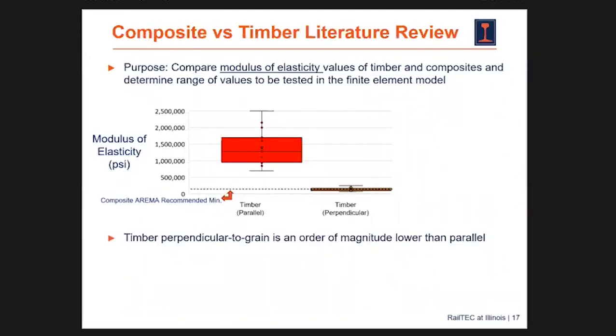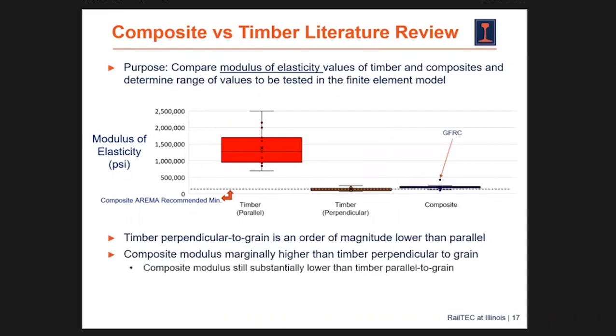So where do composite ties fit relative to timber? If we look at modulus of elasticity, the first thing we notice when we compare parallel to grain to perpendicular to grain, that again, I alluded to this, there's an order of magnitude difference. It's about 1/10 the level. So that means it's a lot more squishy. And composites, yeah, they're stronger than timber, or they're more stiff than timber, but not much. Even the GFRC, which happens to be an outlier, is still significantly lower than the timber parallel to grain.